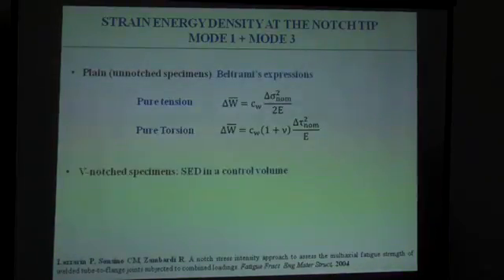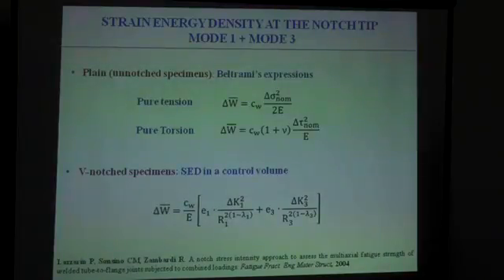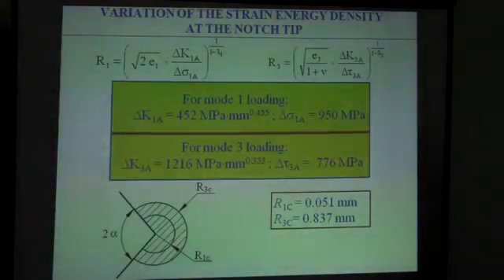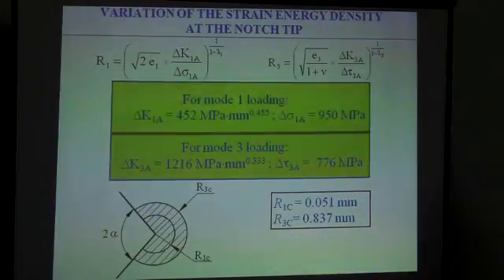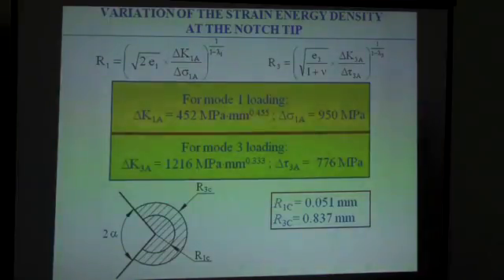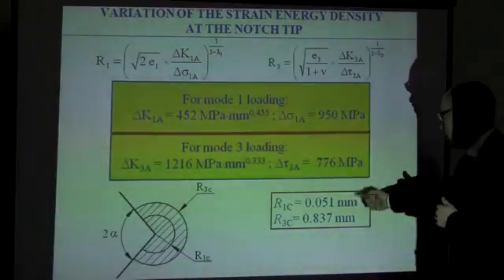And in particular, for plain specimens, we use directly the Beltrami expression, and for notched specimens, we use the strain energy density in the control volume. Before applying the criterion, we have to evaluate the critical radius for the two materials. And what we have found is that the two materials have very different critical radius.